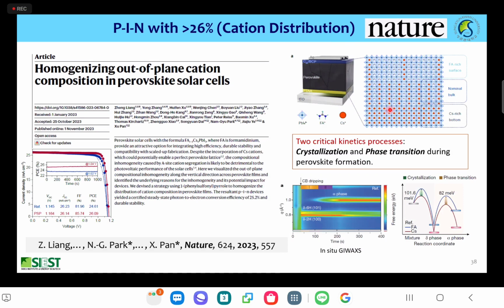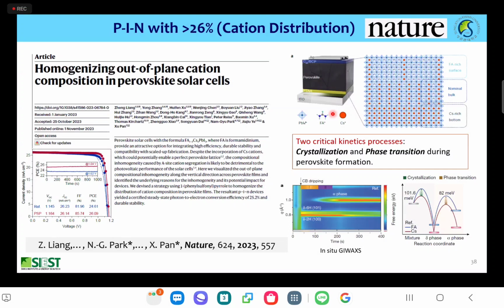For instance, we use the FAPbI3. The single phase is very difficult to stabilize at room temperature. But to stabilize the FAPbI3 alpha phase, we use a small amount of cesium cation. But in that case, the FA cation and cesium cation are not homogeneously distributed across the perovskite film. The upper part of the perovskite film contains the FA-rich phase, and the bottom is the cesium-rich phase, and the middle is actually homogeneous.